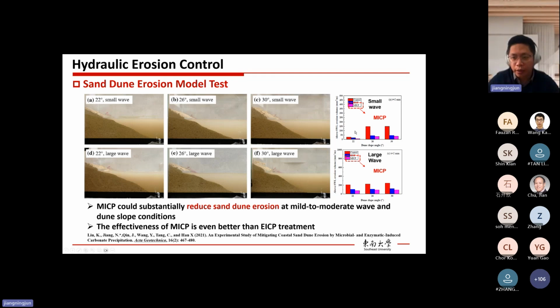From the test results, for both the small wave and large wave cases, the MICP treatment could reduce the erosion volume compared with the red one. The red one is the control case, the untreated case. In this case, we also used EICP to do the treatment, and we found MICP could be even better than EICP in all cases.